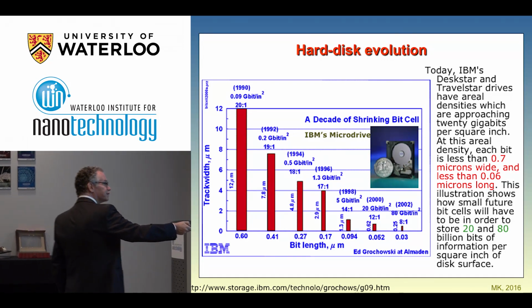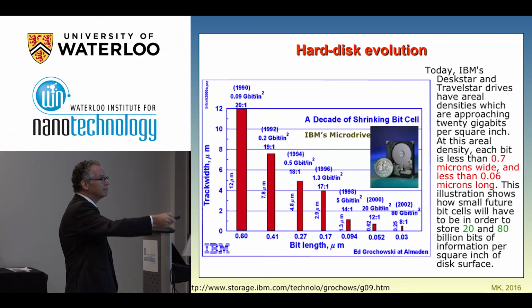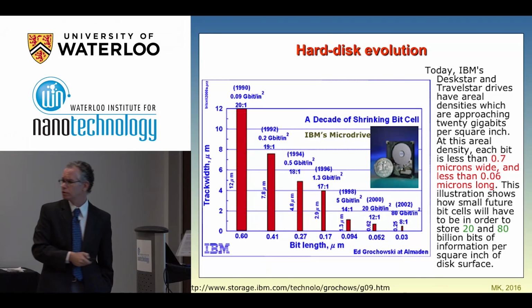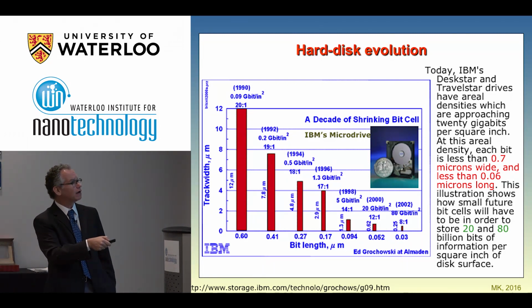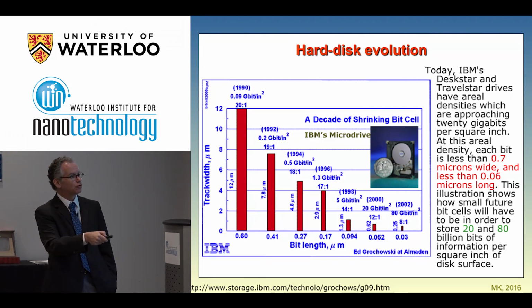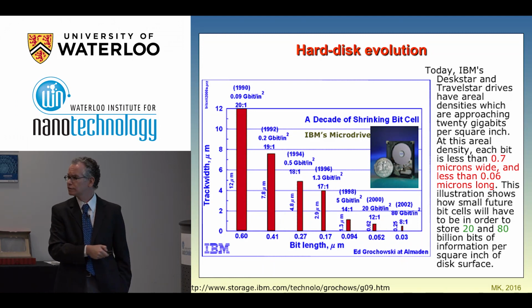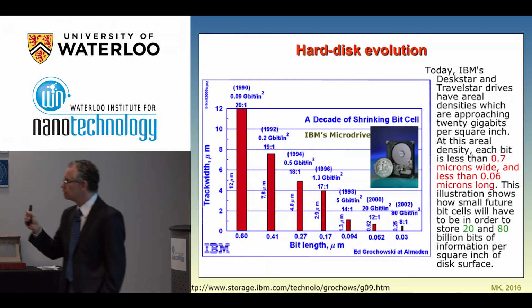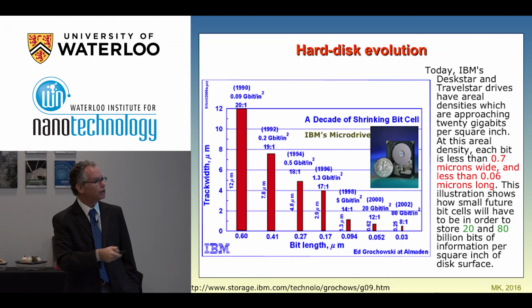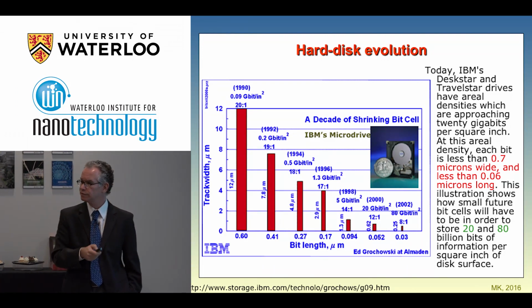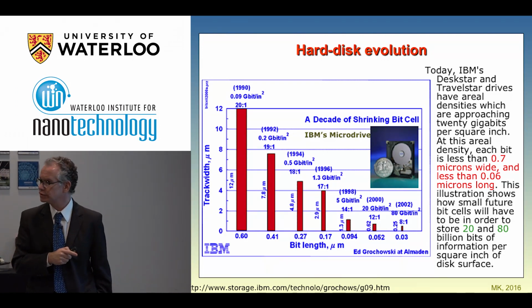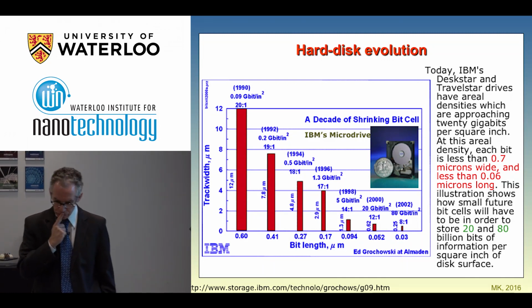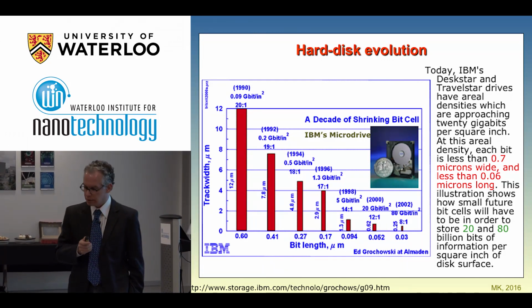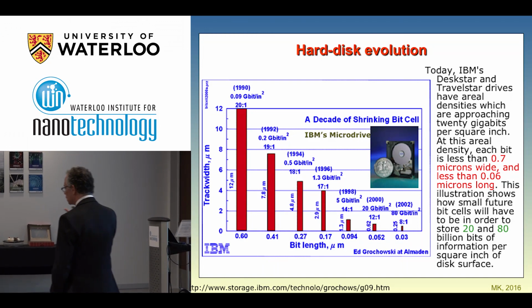And this was 0.6 micrometers times 12 micrometers long. And just after 10 years, essentially 12 years, this was reduced to 30 nanometers by 250 nanometers long. So this was a reduction of a bit size in a window of about 12 years. This is in the commercial hard disks. This is also for the ones that are older here.